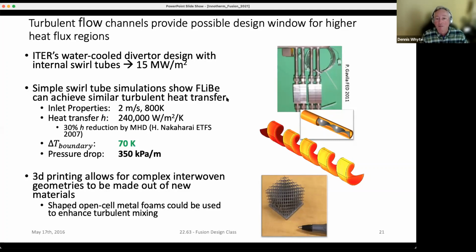And here you can see some examples of this. Swirl tube technology has allowed surface heat fluxes up to 15 megawatts per square meter with water. Our indication was that the salt was similar to that, but it was a pretty simple one. We also started considering using 3D printing for the construction of this vacuum vessel, because it would allow us to build in internal swirl tubes, or good structural meshes that would induce turbulent heat transfer and so forth.